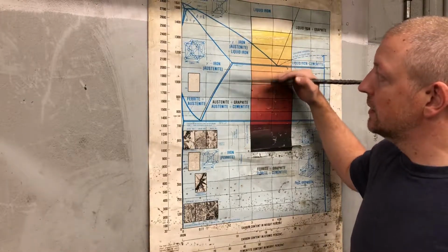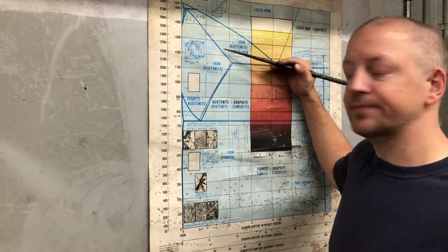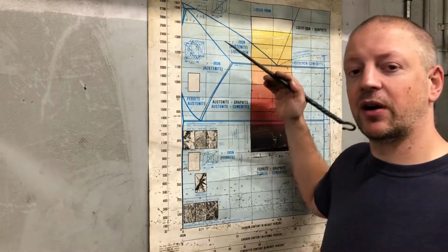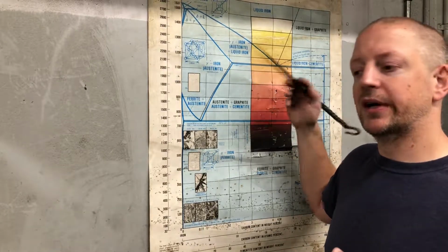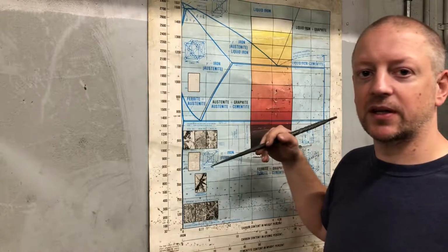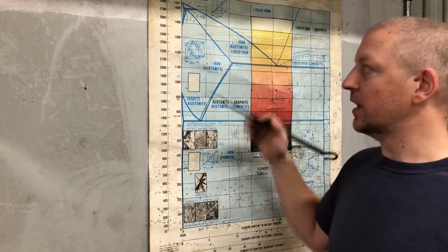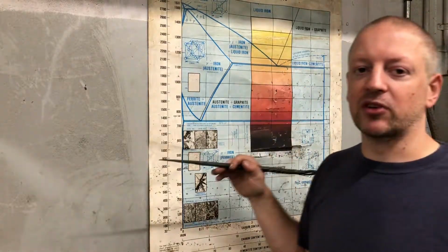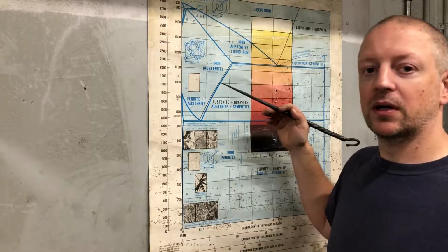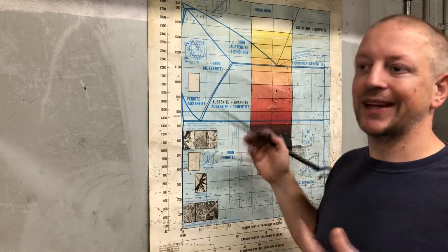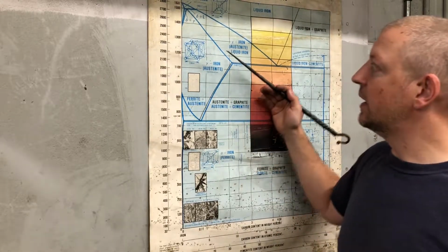But that's not actually why wootz traditionally was very hard to forge. It was traditionally very hard to forge because of other impurities such as phosphorus. Phosphorus does some funny stuff to grain boundaries. You get some other compounds in there, and basically you get a very low temperature liquid compound that, again, creates kind of that bag of wet sand effect.